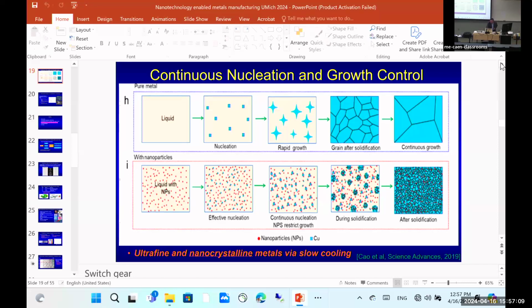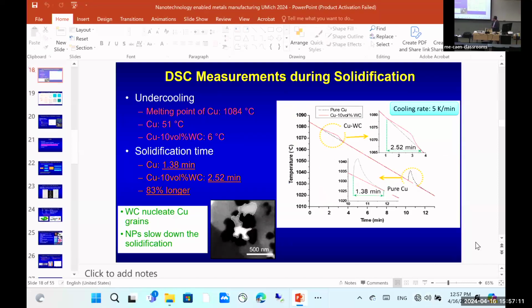So that's the way we can see it. We have one I didn't show here, maybe. You can see the heat release, that's the evidence we get. For example, with nanoparticles the heat release is very gradual. Without nanoparticles, very rapid, because natural free growth is like that. So I win, I quickly release latent heat, kill all the competitors, I occupy as much space as possible, the dendrite grows, right? But the nano stuff doesn't allow you to go there. It only allows you slowly. And that's exactly the key scientific reason we eliminate hot cracking, because latent heat is released very gradually and liquid continues to flow.